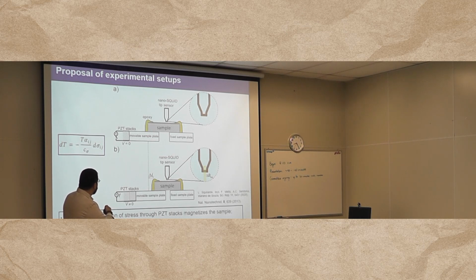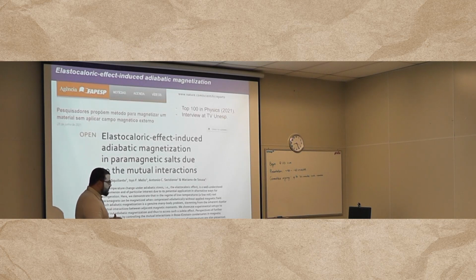And then we made use of this to propose that this can be used to increase temperature adiabatically, but how would we detect the adiabatic magnetization? We have proposed that we can use a nanoSQUID tip sensor. This is work from the Israeli group of Eli Zeldov. They have a SQUID of nanometric scale that is able to capture variations of magnetic fields in the range of nanotesla. So here we have proposed this experimental setup to not only increase temperature adiabatically, which in turn gives rise to adiabatic magnetization, but also to detect the subtle effects. Okay? So this gives another interesting work, a nice publication in Scientific Reports.